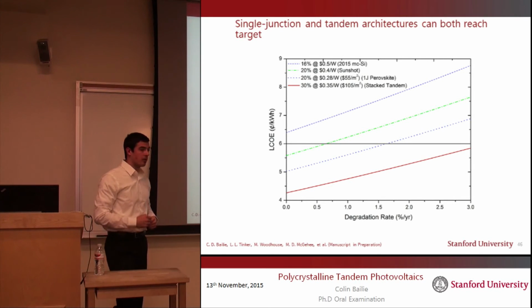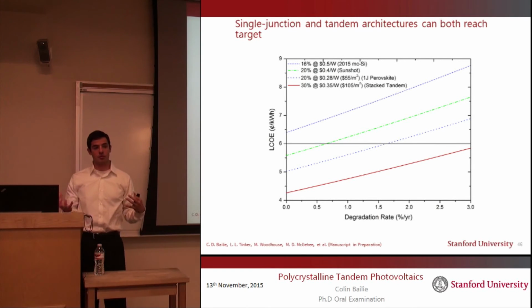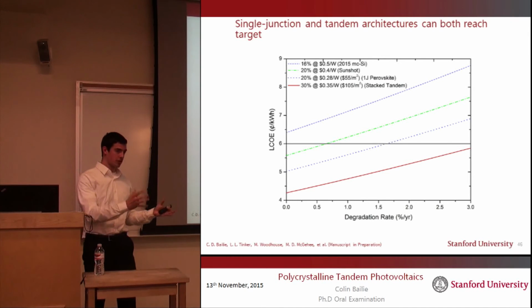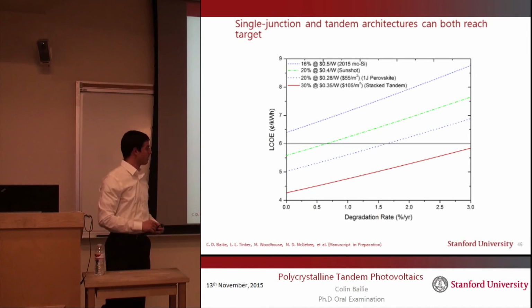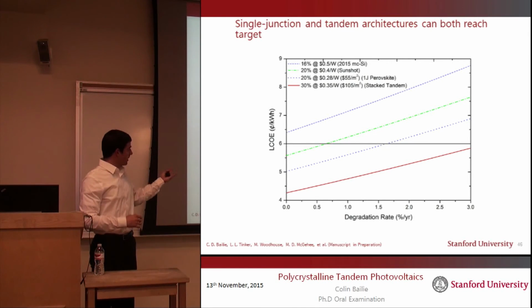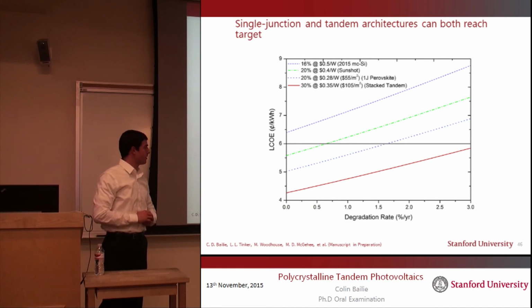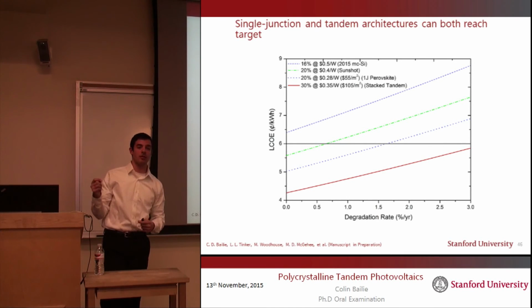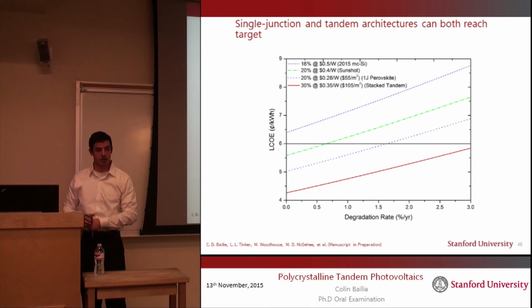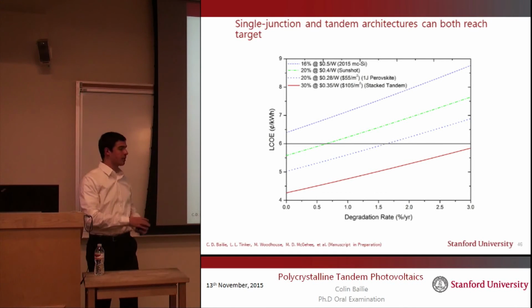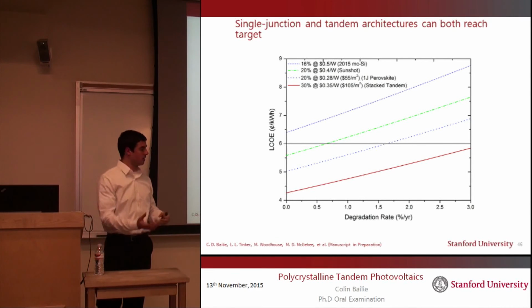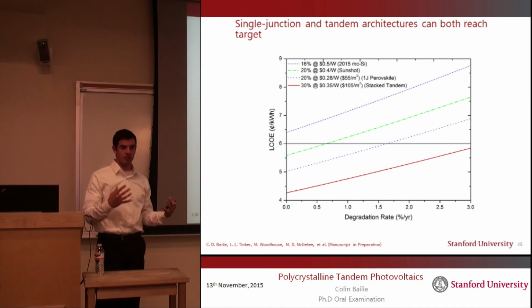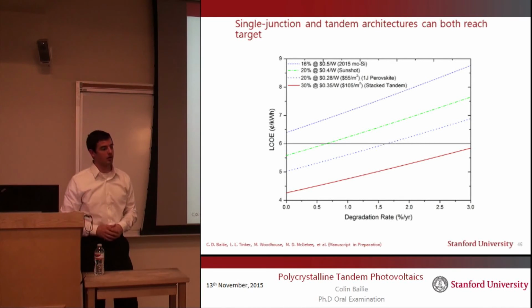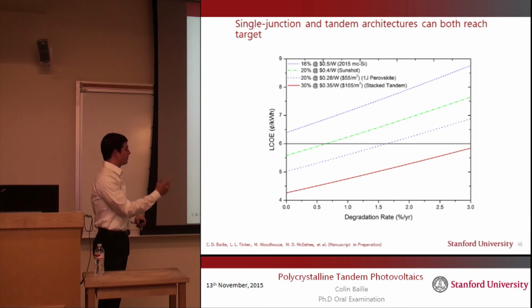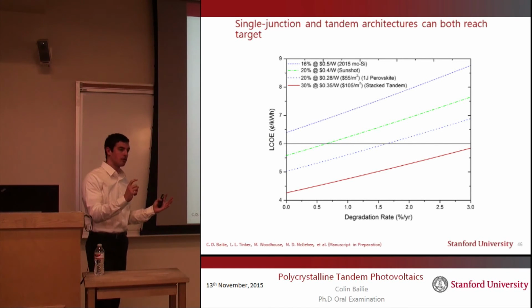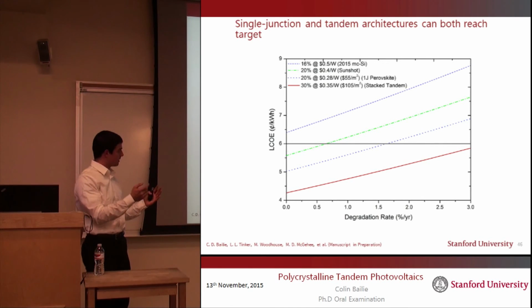The dotted line below it is the results of the cost modeling of the single junction perovskite that we did a couple slides back. And at 20% efficiency and $55 per meter squared, you can reach that 6 cents per kilowatt hour target and afford a significantly higher degradation rate than you could with the silicon. And so this is a clear advantage over the incumbent, but doesn't change the game in terms of choice between